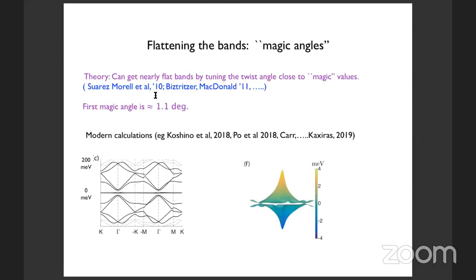Now, as part of the same body of work, people realized that these reconstructed bands become very flat if you tune the twist angle close to some magic values. The paper that did this in the most microscopically accurate manner was by Bistritzer and MacDonald nearly 10 years back. They found that the first magic angle is at about 1.1 degrees, and they produced a band structure at this magic angle.